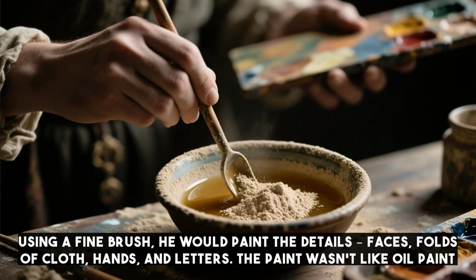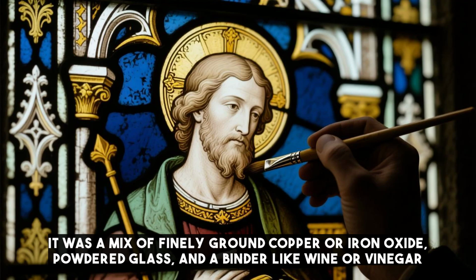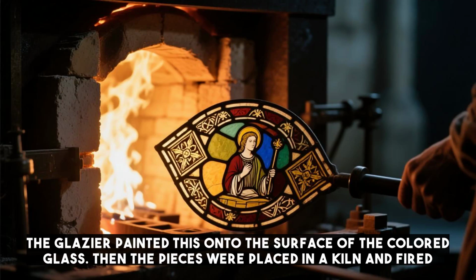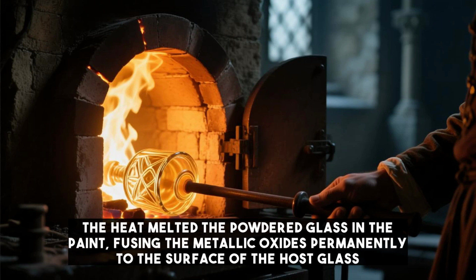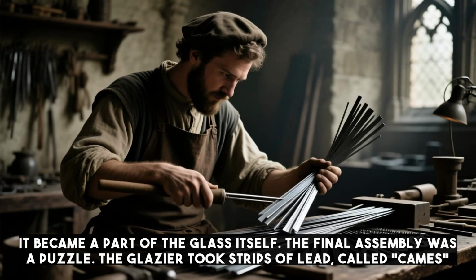The paint wasn't like oil paint. It was a mix of finely ground copper or iron oxide, powdered glass, and a binder like wine or vinegar. The glazier painted this onto the surface of the colored glass. Then the pieces were placed in a kiln and fired. The heat melted the powdered glass in the paint, fusing the metallic oxides permanently to the surface of the host glass. It became a part of the glass itself.